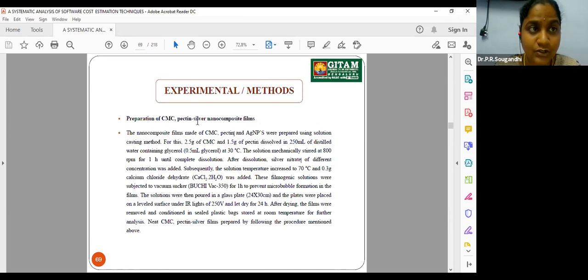After the complete dissolution, by the process of stirring, we add the silver nanoparticles, which are prepared by the green synthesis method, and then everything is stirred, and then calcium chloride is added to it. After that, the solution is subjected to a vacuum pump to remove the micro bubbles present in it. After that, it is kept for drying under UV light or IR light. Later, after the drying, we get a neat CMC silver film prepared by the wet casting method. This is the method of preparation.